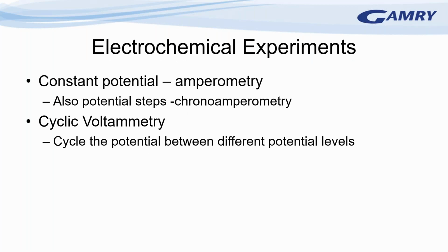So the common electrochemical experiments of interest for spectroelectrochemistry, although this is not an exhaustive list, are something like, as Sergey showed, constant potential amperometry, where you hold a constant state, or potential steps, called chronoamperometry, where you step the potential to different levels, and also cyclic voltammetry, where the potential is cycled between several limits at a constant rate or scan rate. Linear sweep voltammetry, which is a subset of cyclic voltammetry, may also be of interest.